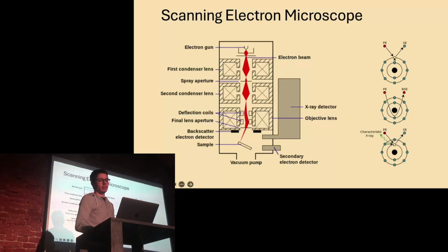Then there is elastic scattering. During the elastic scattering, we've got the backscatter electron, which has energy quite similar to the primary beam, and this usually brings us information about the composition of the sample, like the chemical composition. And to get the actual chemical composition, we can use X-ray detectors, because you probably remember it from chemistry. When the electron exits some inner shell of the atom, it's in an excited state, and during the de-excitation it emits a characteristic X-ray, and this X-ray energy is characteristic for each chemical element. So we can detect the chemical composition of the sample.